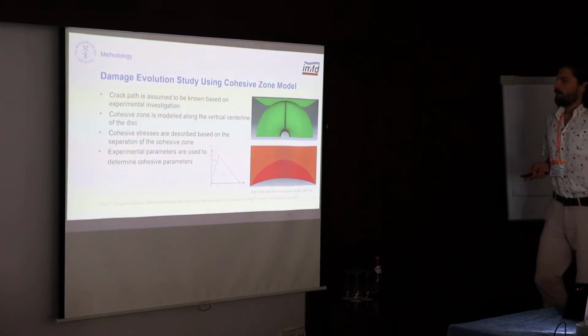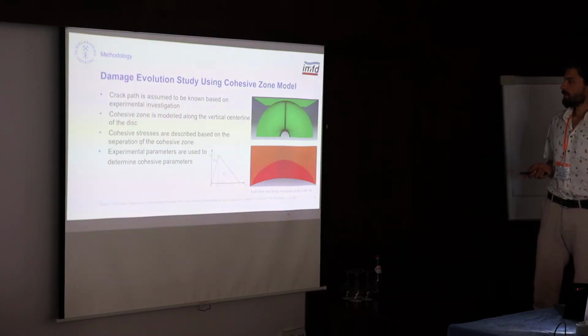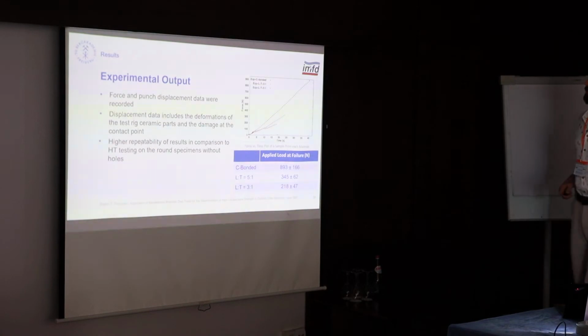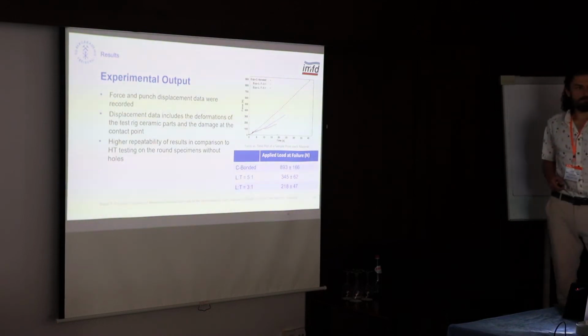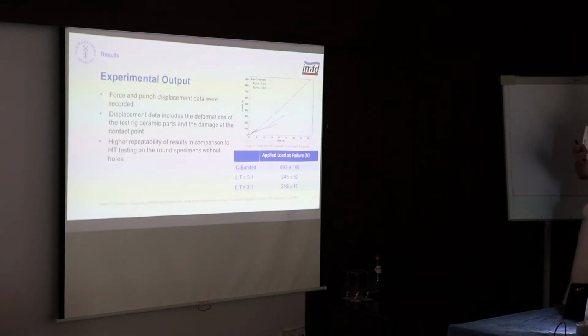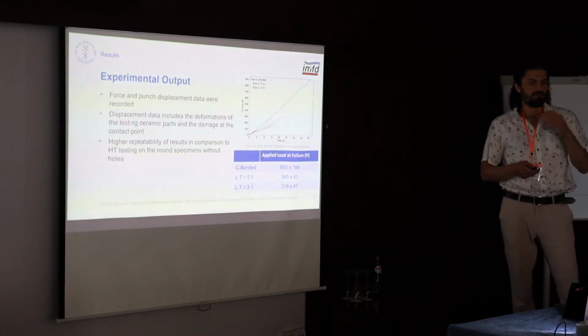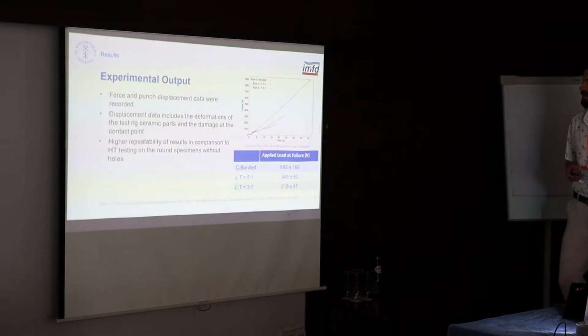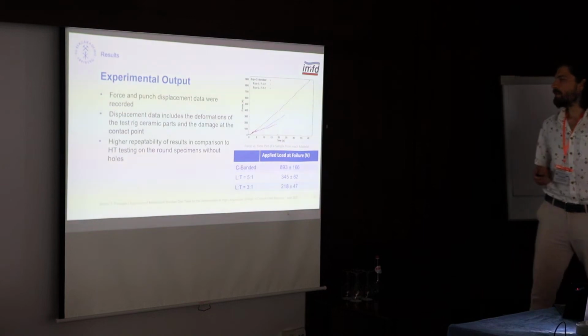And from here, these are my experimental results. You can see three different typical curves for the force values that cause the failure of the three different materials. And before doing the specimen with the hole inside, I did the intact specimens, and they had much bigger scatter in the results. So this variation of the test was also good with the accuracy and repeatability of the test results.